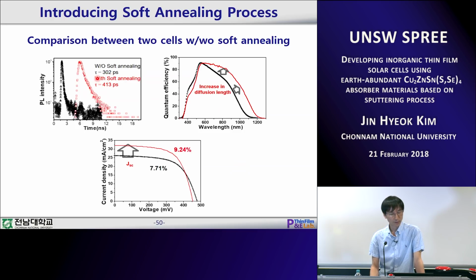We think that because of this minority charge carrier lifetime difference, we could have a high EQE value at long wavelengths, and this gives a high current density in pre-annealed samples. That gives a 9.2% cell efficiency compared with 7.7% for the samples that were not pre-annealed.